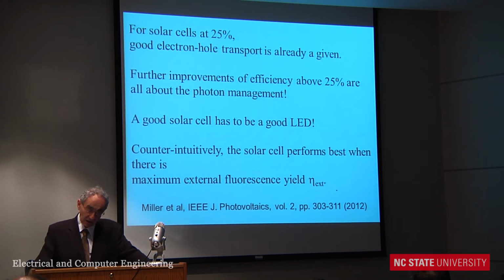So to summarize this part, if you have a solar cell of 25% efficiency, stop worrying about electron hole transport. Don't even bother with that in your solar cell model. If you want to go above 25%, it's all about photon management. It's all about assisting the internal photons to escape and to emit externally. In fact, there's a mantra that came out of this. And the mantra is, a good solar cell has to be a good LED, and a great solar cell has to be a great LED. Okay? And so the way to make the highest voltage is to get the best external LED efficiency.